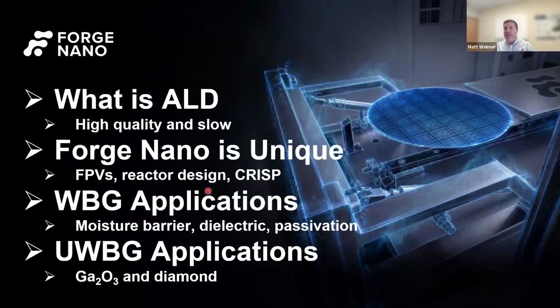All right, I have about 2 minutes left, so without repeating myself too much, ALD is a wonderful technique, very high quality film, very elegant, but it's slow. The good thing is we have a reactor that helps speed things up, both in the R&D space, where we do more experiments, as well as in the manufacturing space, processing more wafers per hour. We've applied our technology to wide band gap applications of silicon carbide and gallium nitride. Again, the three key ones are moisture barrier, dielectric film, and passivation. And we've started to explore some ultra wide band gap materials, gallium oxide and diamond.